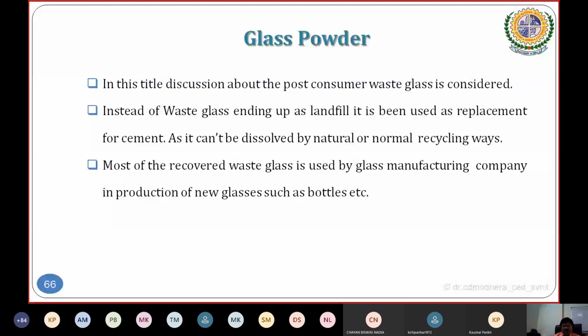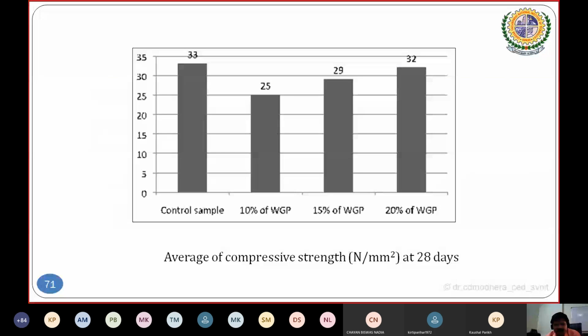Here, one typical glass powder concrete mix given was just M20: cement 330 kg per meter cube, sand 770 kg per meter cube, aggregate 1190. The water-cement ratio of 0.52 has been mentioned. WGP indicates waste glass powder. When we use secondary materials you will not have that much benefit, but we have tried 10%, 15% and 20%.